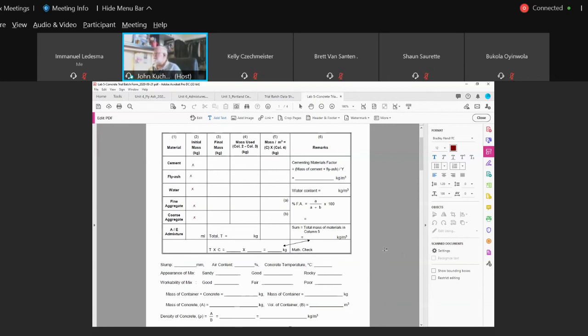A 10 to 30 range would work for temperature, closer probably to 20, not 30, because you're mixing water. CSA actually has temperature criteria that your concrete should be at, depending on the thickness of your structure. If you go through CSA, those tables at the end of A23.1, we have all those tables. Remember, you looked at the tables for gradations and exposure conditions.